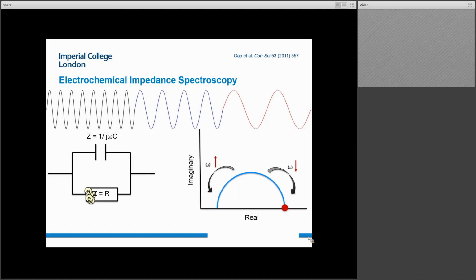So what's actually happening in this system? The semicircle that we have is what we would expect to see based on this type of circuit. The diameter of the semicircle is the resistance to charge transfer, and the gap you see between zero and the start of the semicircle is what we would have as resistance to solution, which I didn't show in this illustration. But hopefully you can see the pieces in this ideal system.